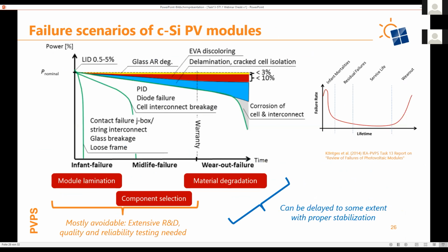Because when you look at typical failure scenarios of silicon PV modules, then you see you have infant failures, you have midlife failures, and you have wear-out failures. Wear-out is mostly dependent on material degradation. It can be delayed to some extent, but it cannot be avoided totally. So we will always have material degradation. But infant failures are very often correlated to bad lamination, like bad processing. And midlife failures are also very often correlated to bad component selection.